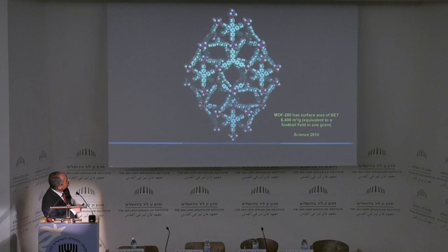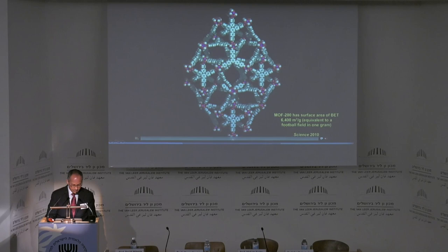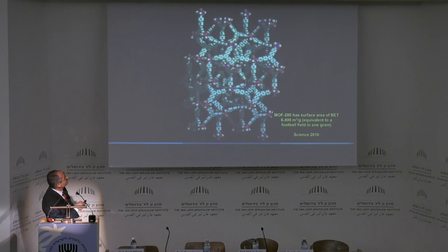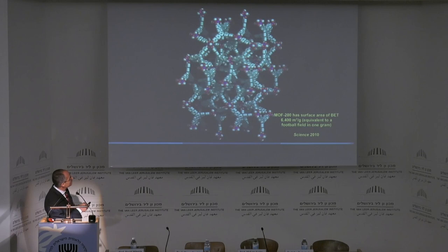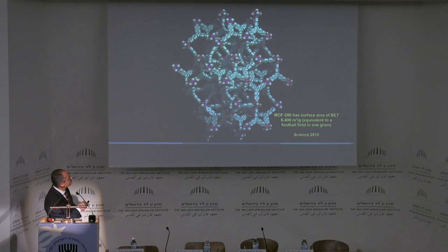So here's a typical MOF, where everything you're looking at, whether it's the organic linker or the metal oxide units, is an adsorptive site. This structure is supposed to be rotating. Okay, that works. MOFs, unlike other porous materials, the pores have no walls, so things can diffuse in and out with great facility. The pores never get clogged. And as I said, the fact that everything you're looking at is a surface, is an adsorptive site, gives you extremely high surface area.